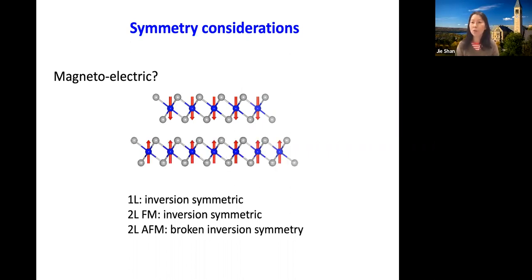So now if we go to 2 layers, the structure itself still has a center of inversion. So I can put my point here. You can find symmetry between the top and the bottom layer. However, if we include all the spins, as I mentioned, under inversion, spin doesn't change. Therefore, if the 2 layers are both ferromagnetic, we have an inversion symmetric structure. However, in the antiferromagnetic bilayer, inversion symmetry is broken.